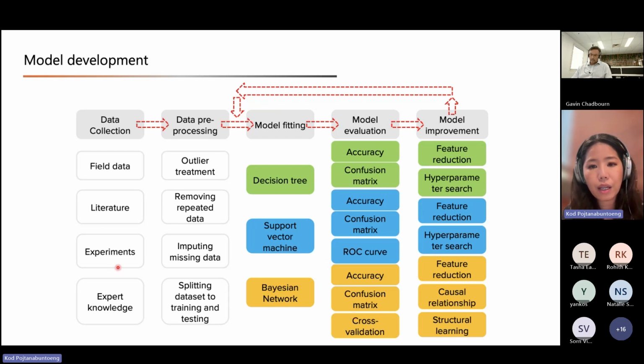In this case, we have Fremantle Ports as the source of our field data, from the maintenance records that Fremantle Ports has. Sam developed the database from the literature using not experimental data, but more the field data reported within the literature around the world, especially for the marine environment. The experiments as well, with a little caveat: there's always a question whether the experimental conditions can simulate the actual scenarios. So our model relies on the field data and the literature based on field data.